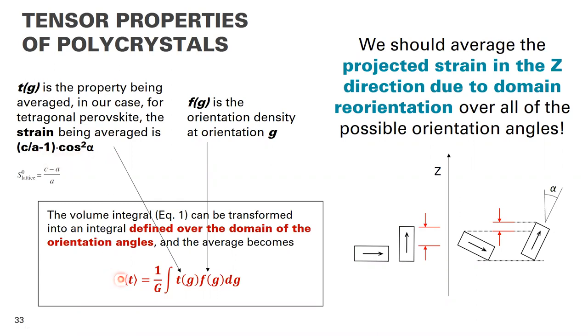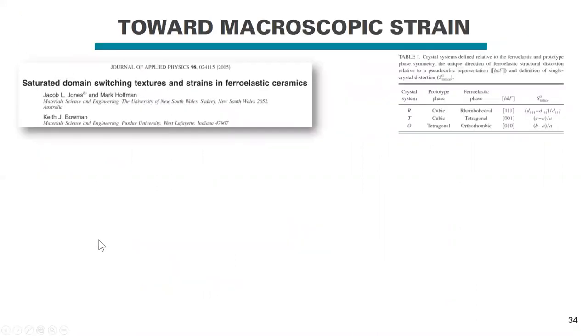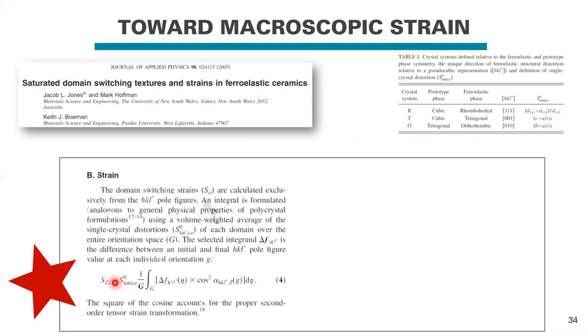Okay. So pulling all this together, we were able to create that important equation. We published it in this paper, and we calculated the saturated strains that would result from three different crystal systems. So the strain equation that I showed early, that I called a rabbit hole, is here. The domain switching strains are calculated exclusively from the pole figures. An integral is formulated analogous to the general physical properties that we showed on the previous slide, using this volume weighted average of single crystal distortions over the entire orientation space G.